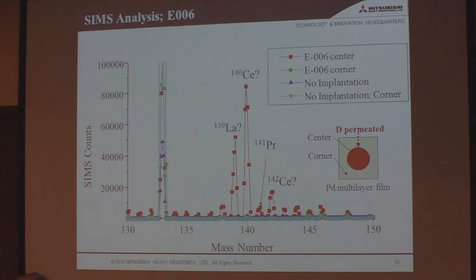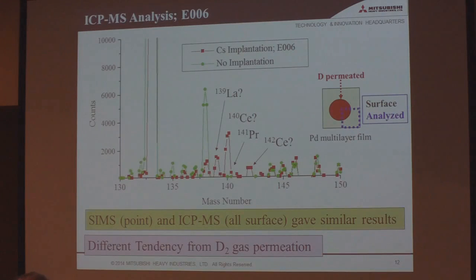So we confirmed this by another method, the ICP mass spectrometry method. We analyzed the center and corner regions. And we can see that praseodymium or cerium mass numbers also increase around here. So SIMS and ICP mass gave similar results.